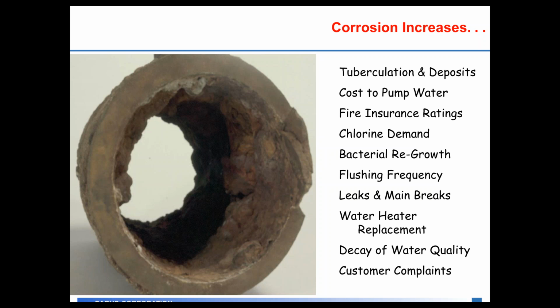As that scale and tuberculation builds in the system, it'll actually influence your chlorine demand in the distribution system. Chlorine will interact with that scale. You'll have a loss of disinfectant residual, and you'll have to feed more and more chlorine at the plant to maintain the same chlorine residual throughout the distribution system. If it gets really bad, you can have bacterial regrowth out in the distribution system. The bacteria, specifically iron bacteria, like to hide in that iron scale tuberculation and can cause red water episodes out in the distribution system.